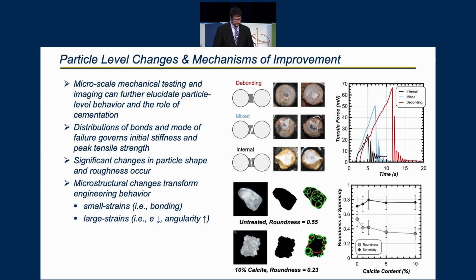Microscale mechanical testing can really help us understand what is going on at the particle level, and in particular, the role of cementation towards enhancing macroscale engineering behaviors. For example, we can see from two-particle tensile tests that both the distributions of bonds and their mode of failure can govern behaviors such as initial stiffness and peak tensile strength, with debonding of cementation from particle surfaces affording greater strength than internal failure of cemented bonds.